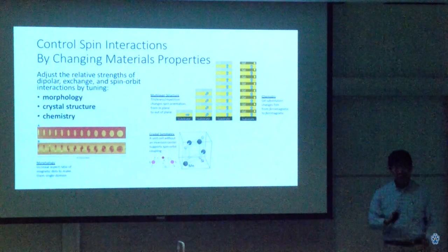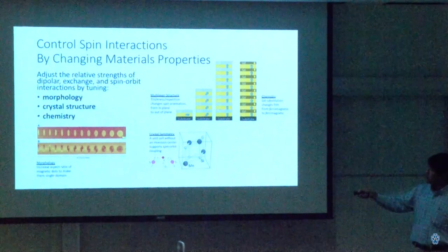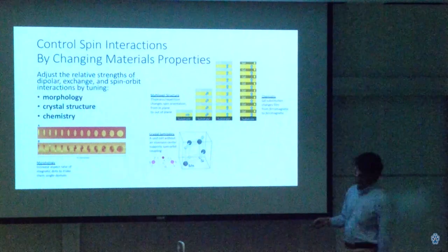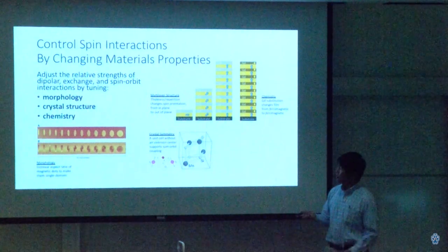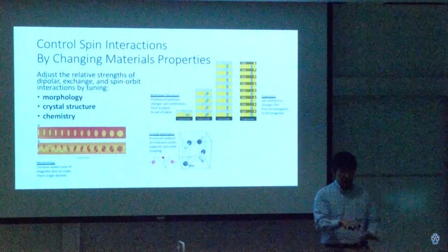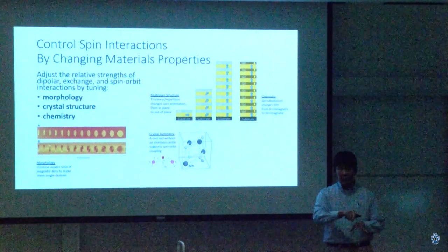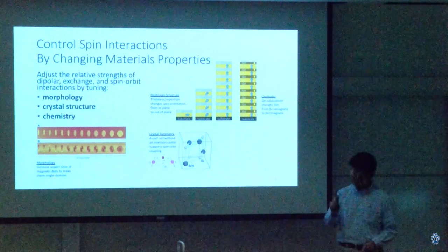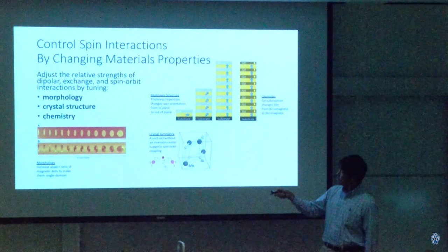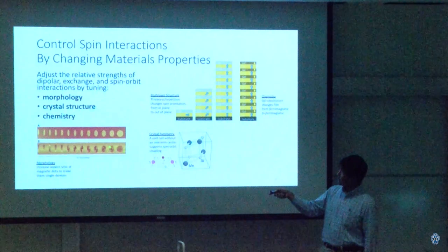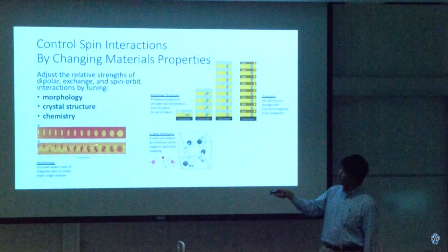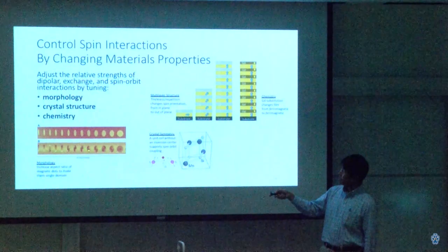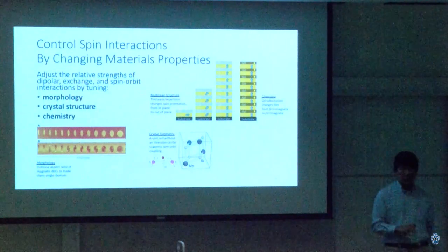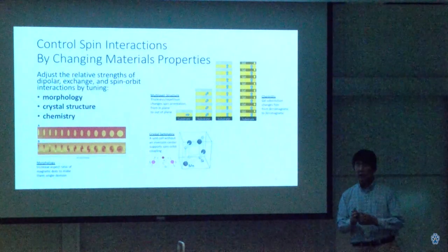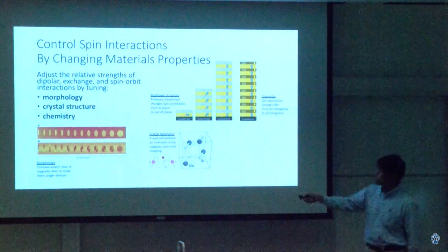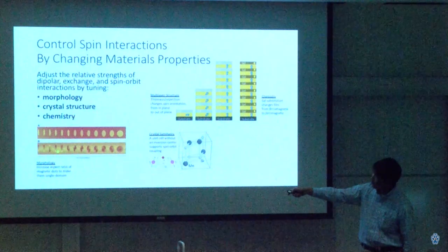You can tell I'm hungry because I'm now thinking in terms of food. But you can see how the aspect ratio has changed right to left. In an experimental probe called magnetic force microscopy, which can directly see how the magnetic domain points, at least inside the plane or outside the plane of their system, going from right to left, you can see that there are light and dark patches appearing. And these resemble the closure domains I showed you earlier in the iron whisker, as well as a textbook example of magnetic domains. But watch what happens between this one and this one.